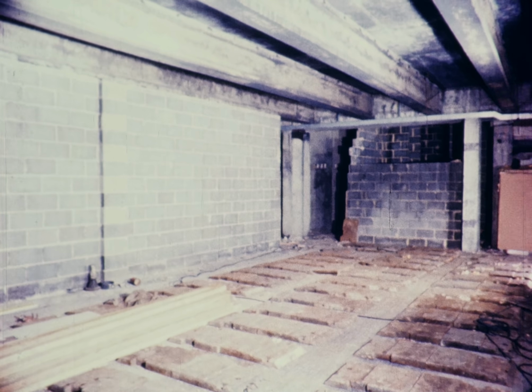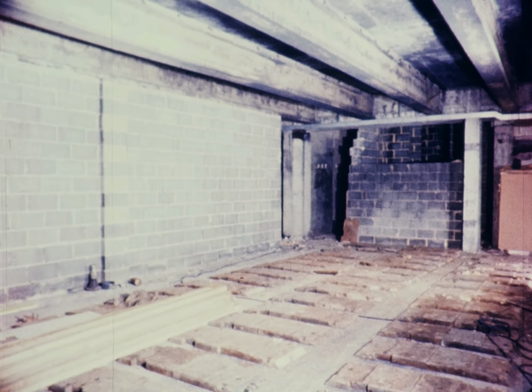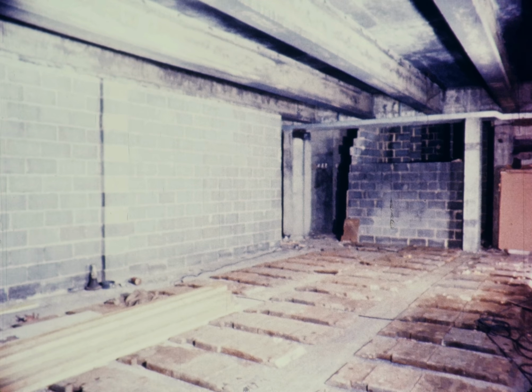A fire that occurred while this building was under construction caused the concrete to spall away from the corners of the beams, exposing the reinforcing steel. Concrete also spalled away from the ceiling. Once the steel is exposed to fire, its temperature can rise sharply. Collapse could have occurred if the fire had continued, since steel loses its strength when it gets hot, as is shown by the bending and twisting of unprotected steelwork in a fierce fire.